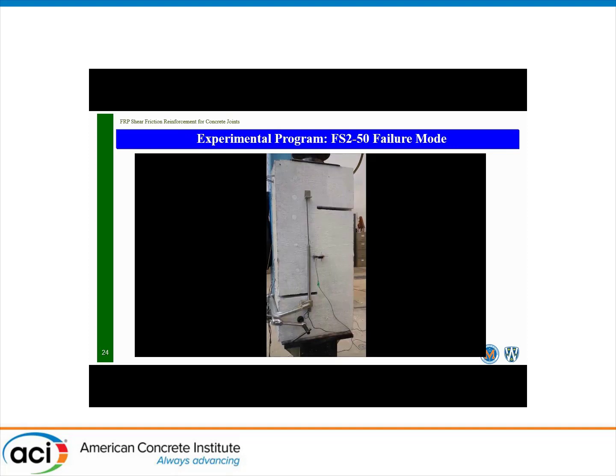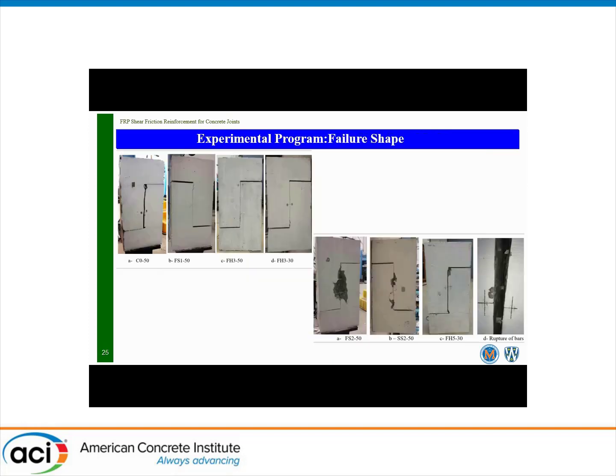While the one reinforced with 2 GFRP stirrups, the specimen is still able to carry much load and sustain that load for a long time after failure, at the expense, of course, of more strain and more dilation in the specimen itself.